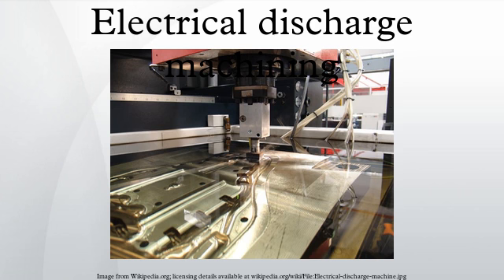The reason that the cutting width is greater than the width of the wire is because sparking occurs from the sides of the wire to the workpiece, causing erosion. This overcut is necessary. For many applications it is adequately predictable and therefore can be compensated for. Spools of wire are longer. An 8 kg spool of 0.25 mm wire is just over 19 km in length. Wire diameter can be as small as 20 micrometers and the geometry precision is not far from +/- 1 micrometer.